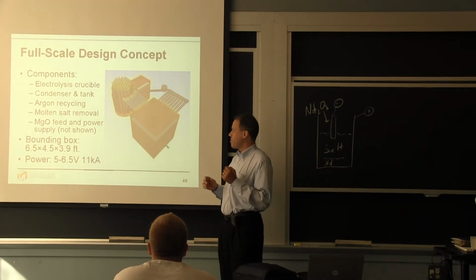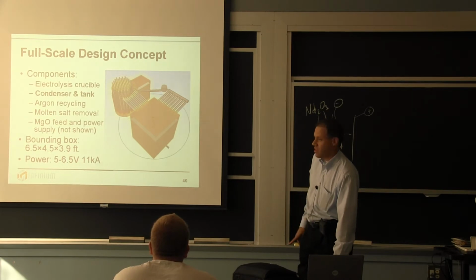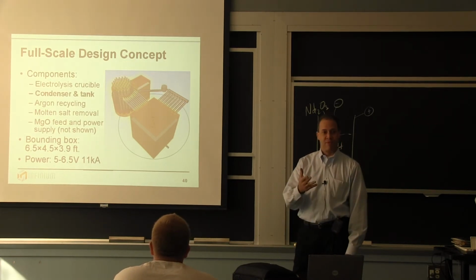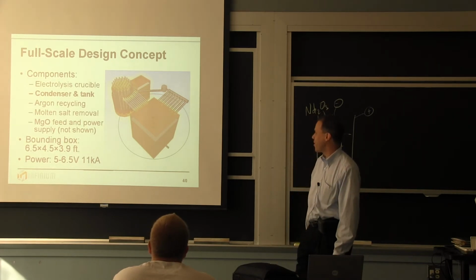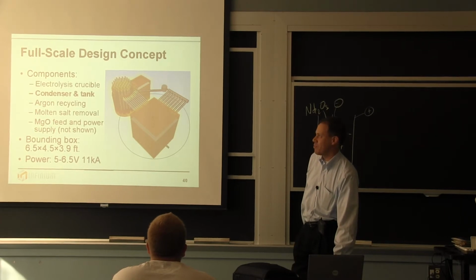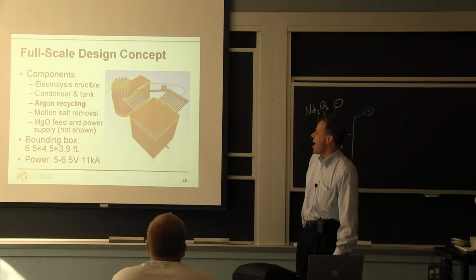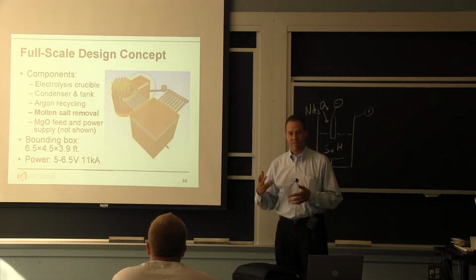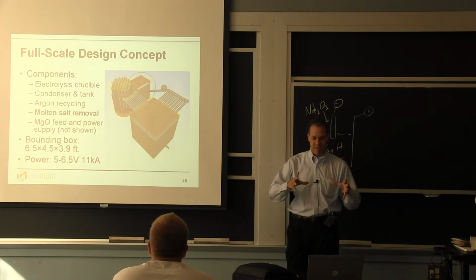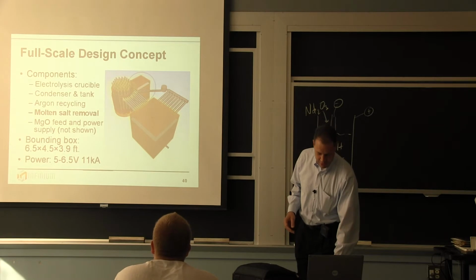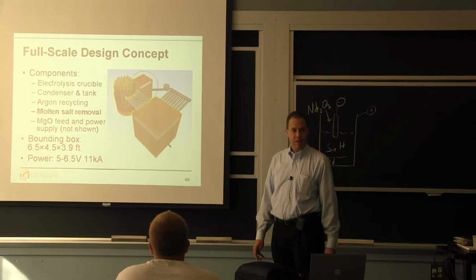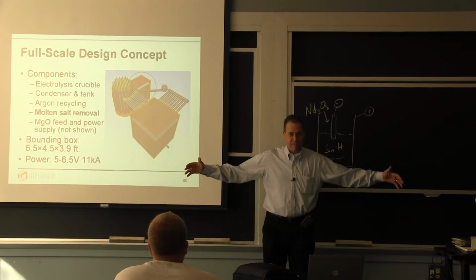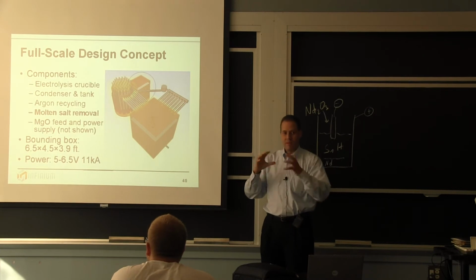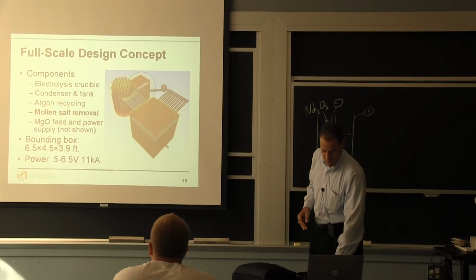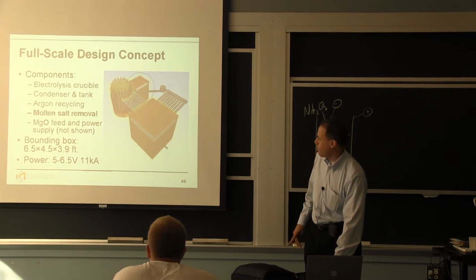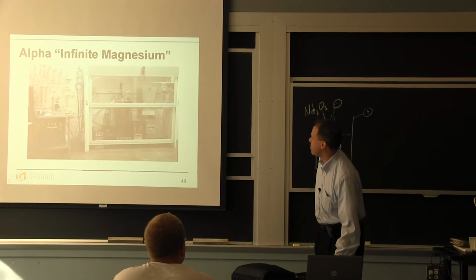So you see the crucible with all the tubes in the top left, condenser and tank for the metal. We have a 2-stage condenser. Actually, an intern from the Material Science Department helped to invent it a few years ago. So he's on our patent application, which is about to be granted. But anyway, Tom is also an inventor there. Argon recycling, and I didn't mention this, but because of impurities in the molten salt, you have to continuously remove some of the molten salt. So it's about a 6-month residence time in the cell there. So this is about 40 ton per year cell concept, and fits into a relatively small box. We put it in a box with the heating inside to have an inert atmosphere, so we can just use steel without having to use very expensive stainless steels.